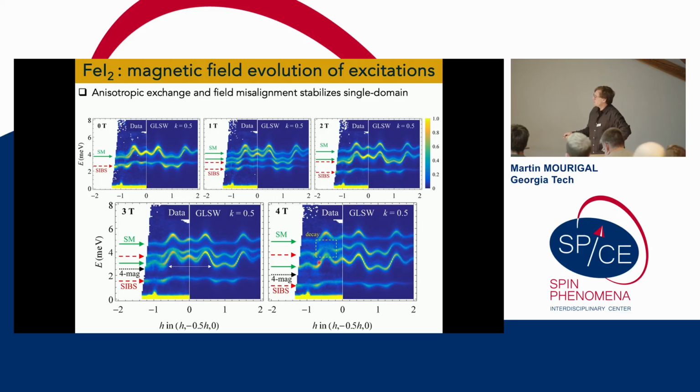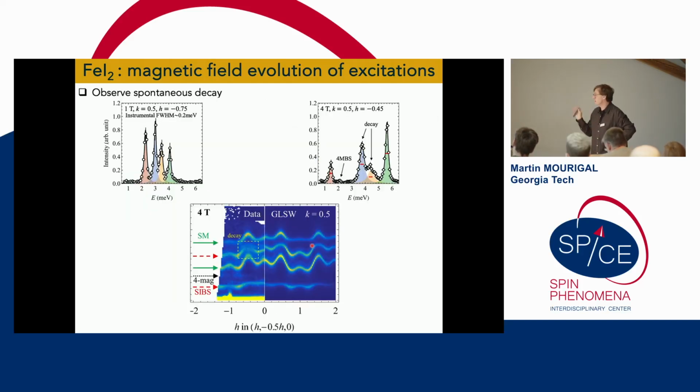And here, perhaps where we least expected, in the spin-1 system that seemingly has a large anisotropy, you see that some of the spin wave dispersion seems to be completely vanishing and becoming very broad. And that's actually a striking example of magnon decay, which is not what we were looking for, and I was not expecting it in that particular material.